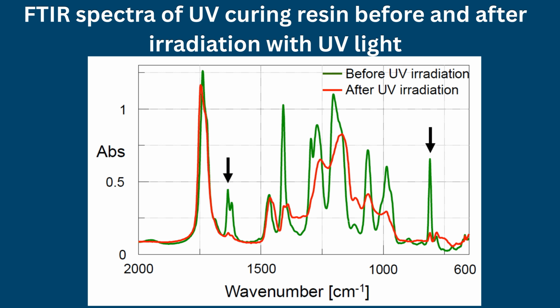810 inverse centimeters or 1,636 inverse centimeters, to determine the conversion percentage. Top surfaces cure faster due to light intensity, while bottom surfaces often show lower cure degrees due to oxygen inhibition, pigment shielding, and UV absorption.